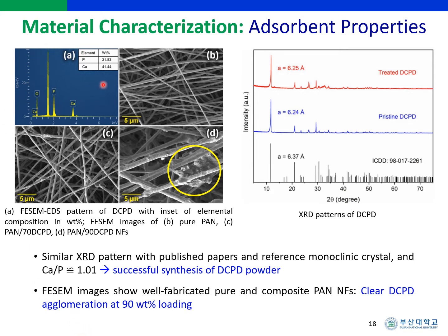The results of the qualitative elemental analysis of adsorbent particles via FE-SEM-EDS depicted in this graph revealed a calcium to phosphate ratio of 1.01. The results of the XRD analysis and FE-SEM-EDS qualitative elemental analysis confirmed the successful preparation of DCPD powder through the wet chemical precipitation method.